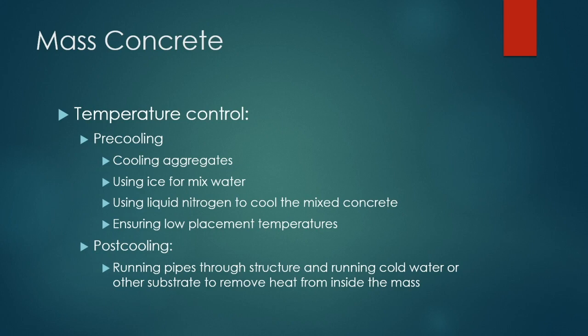The first is what they call pre-cooling. Pre-cooling simply means you're going to cool the aggregates. You're going to potentially use ice for your mix water. You might use liquid nitrogen to cool the mixed concrete, and you're going to ensure low placement temperatures. So what that basically means is, instead of, in the dead of summer, placing your standard 90-degree concrete, you're going to intentionally make that concrete something like maybe 50 or 60 degrees, just because you want that low temperature to start off with, because you've got that adiabatic rise to contend with.